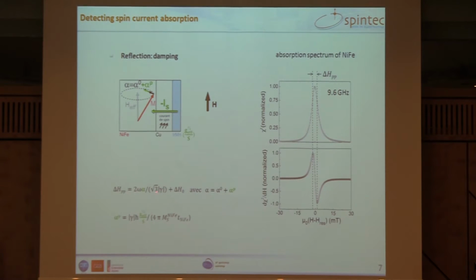And the line width is directly related to the damping of the ferromagnet, which itself contains, say, 2 terms. One, which is the intrinsic damping, and the other one, alpha P, which is the damping related to whatever is absorbed by the neighbors. And since it is related to whatever is absorbed by the neighbors, it is related to this effective spin mixing conductance. So in practice, if we have access to a series of spectra like that, we measure the line widths, and we can work out the alpha pump and the absorption by our antiferromagnet.